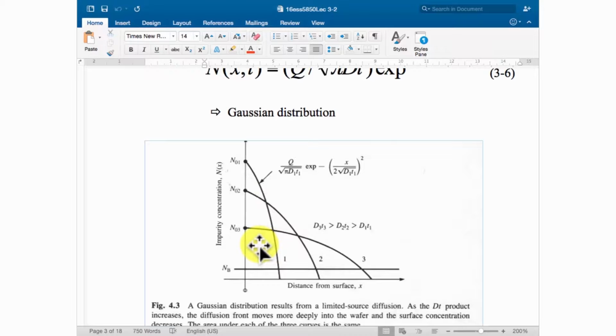That means the total amount of impurity introduced to the substrate will be the same. You have that amount. As time advances, you get a different distribution. Originally, you have a very steep distribution. As time progresses, you get a slower, not that steep distribution. So the concentration on the surface becomes lower and lower, but the penetration becomes deeper and deeper. But the total amount will be the same. So this second type we call the limited source diffusion.